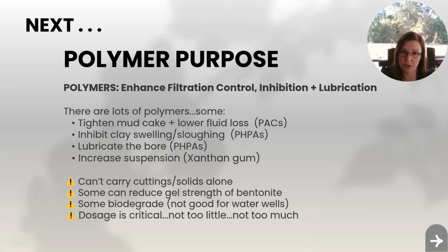That's not part of its function. You need a polymer, and specifically a polymer called PHPA. Okay, I'm going to give you the name of it: partially hydrolyzed polyacrylamides. Now, again, why is it so much easier to say PHPA? But those are the types of products that will wrap themselves around clay cuttings to help you get them out